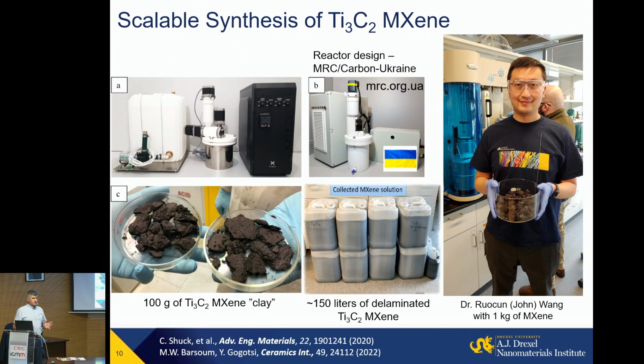But what is also important, many of these methods allow us to produce a large amount of materials. Why am I focusing on this? Because whenever you have materials made of abundant elements and you can make them in a process that is intrinsically scalable, like wet chemical etching, you dump MAX phase powder into a reactor. This reactor was designed by us with Materials Research Center, Ukraine. We get like 100 grams in a single batch of Ti3C2. We call it MXene clay because it has water and ions between the layers. So it rheologically, after using lithium fluoride HCl etching, behaves like clay.